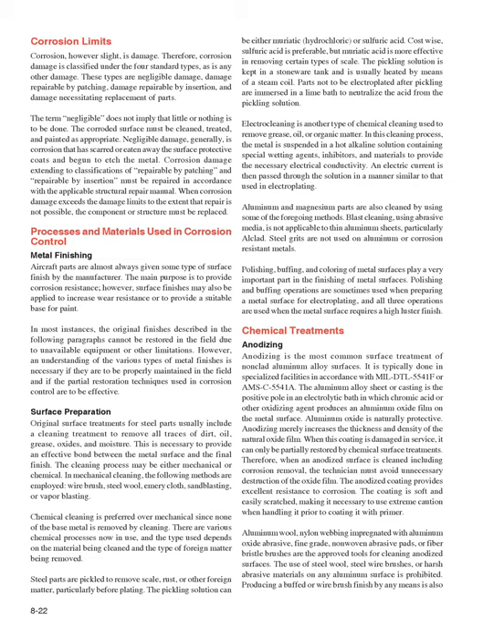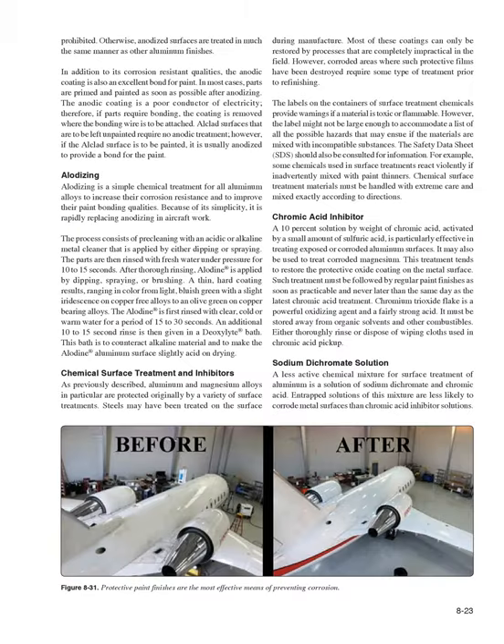The coating is soft and easily scratched, making it necessary to use extreme caution when handling it prior to coating it with primer. Aluminum wool, nylon webbing impregnated with aluminum oxide abrasive, fine grade, non-woven abrasive pads, or fiber bristle brushes are the approved tools for cleaning anodized surfaces. The use of steel wool, steel wire brushes, or harsh abrasive materials on any aluminum surface is prohibited. Producing a buffed or wire brush finish by any means is also prohibited. Otherwise, anodized surfaces are treated in much the same manner as other aluminum finishes.